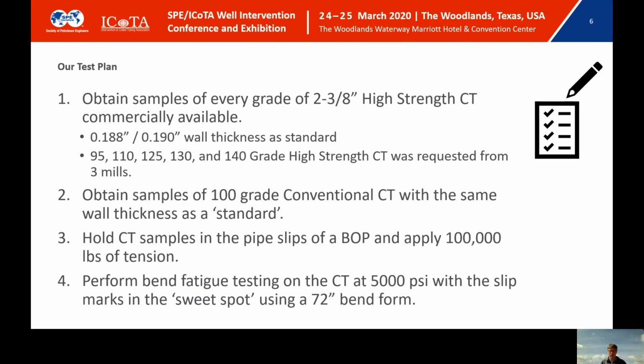and pull 100,000 pounds of tension into the coil, remove the coil, and send it out for bend fatigue testing, and see if we could find a trend or a difference between the conventional sample and the higher grade samples. We chose 5,000 psi, and we used that for all samples, and a 72-inch radius bend form.